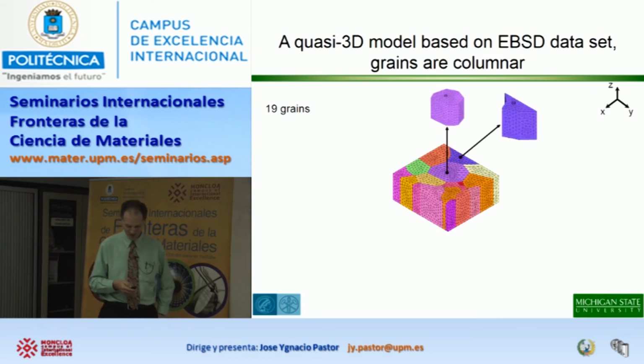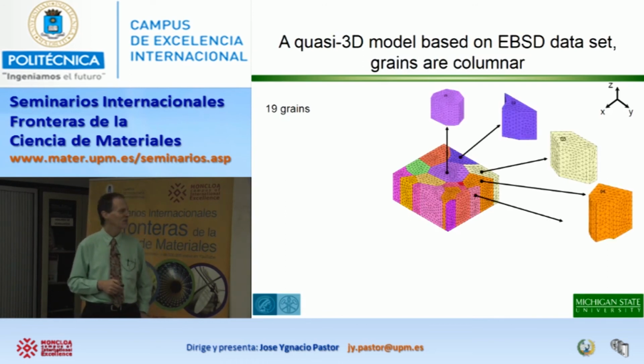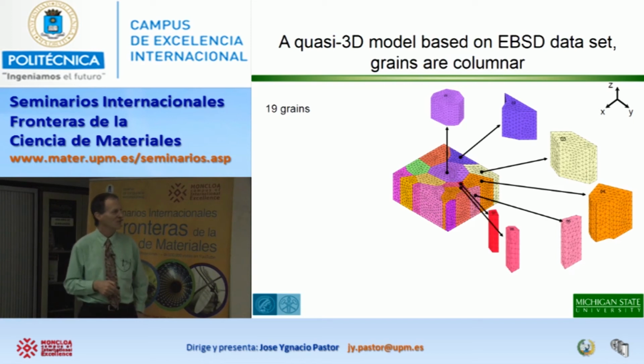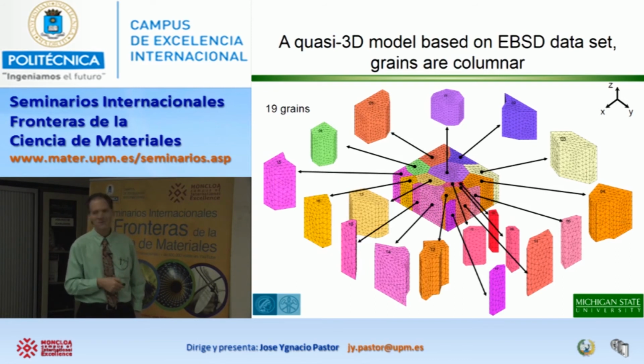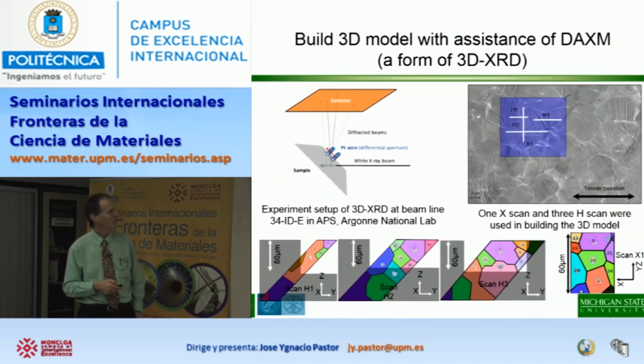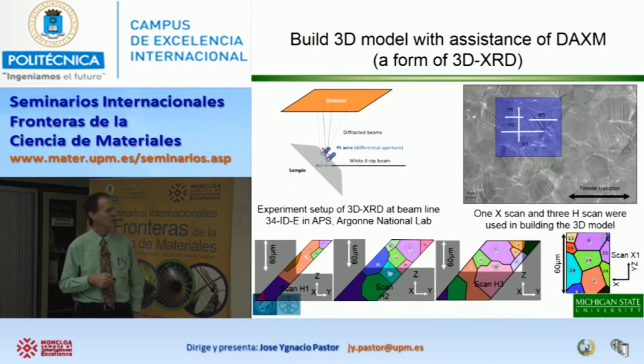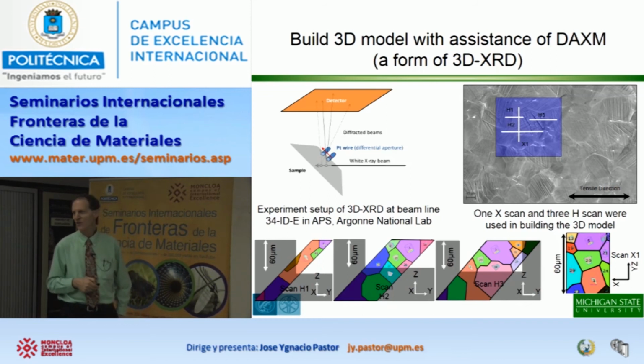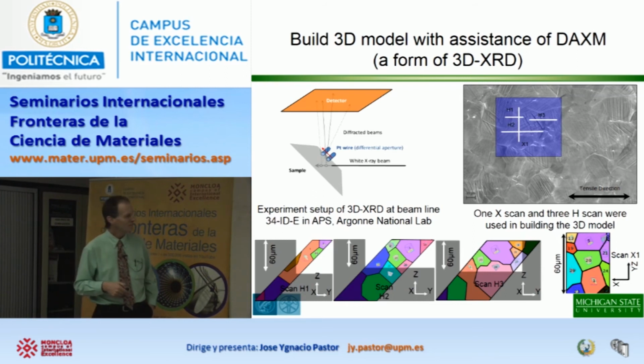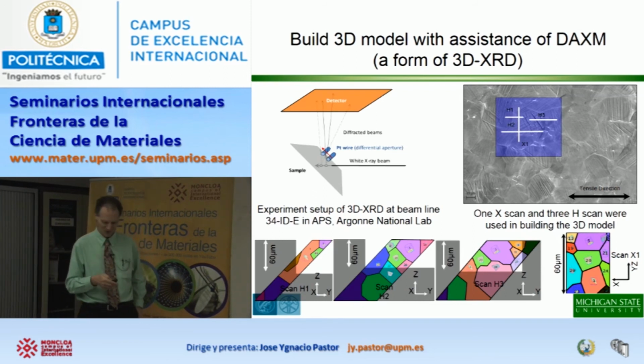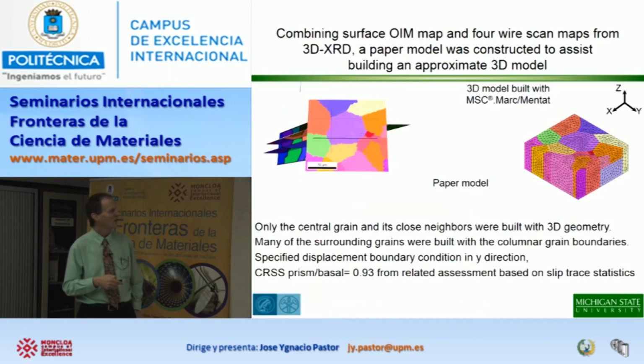So what we did is we took an OIM scan on the surface to get crystal orientations and then created columnar grains and essentially built a model of this. It has 19 grains. But we also took some information we got from a kind of 3D X-ray diffraction in which we can essentially do something like an OIM scan beneath the surface, non-destructively. And so we can get OIM maps. And with a lot of effort,